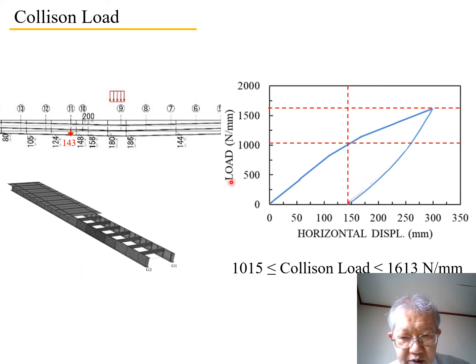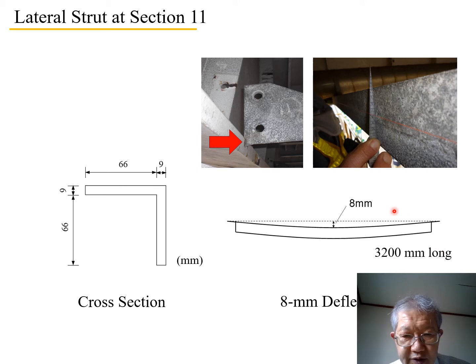This is the result. Load, displacement, horizontal displacement at section 11. We got this relationship. And then from this figure, we can tell that the collision load must be greater than 1015 but smaller than 1613 Newton per millimeter for that phenomenon at cross section 7 to take place. We observe the deflection of the strut at section 11, 8 millimeters, and we believe that this was caused by the contact load coming from the lower flange.